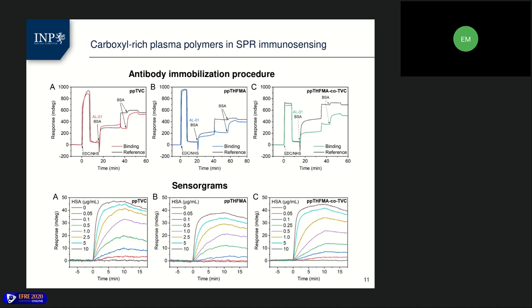During the immunosensor preparation procedure, the level of response of plasma polymer films towards the EDC, NHS activation mixture was similar in all of the cases, but the amount of antibody bound to the surface was different. The largest volume of antibody loaded on the sensor surface was in case of copolymer film, which can be due to a larger surface area resulting from the formation of these donut-like structures that we've seen before.